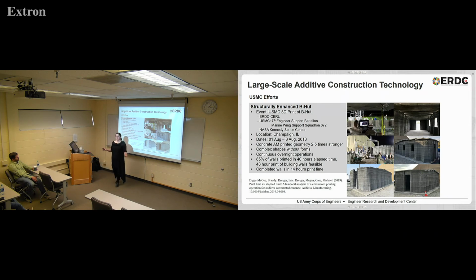Conventional cast roof. It took longer for them to build the formwork for the roofs than it took for us to print the walls. And I don't mean by a little bit. I mean, we basically printed that building in 48 hours, and the roofs took weeks to do. So when you start talking about the speed of construction, that's where it really takes effect: if you don't have to build formwork, that reduces the amount of time it takes to construct a concrete building or other structure.